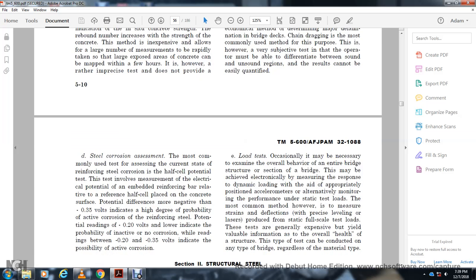Steel corrosion assessment. The most commonly used test for assessment of the current state of reinforcement steel corrosion is the half-cell potential test. The test involves the measurement of electrical potential of the embedded reinforcement bar relative to a reference half-cell placed on the concrete surface. A potential difference more negative than 0.35 volts indicates a higher degree of probability of corrosion activity occurring within the reinforcement steel. A potential reading of -0.2 volts or lower indicates a probability of no corrosion, while a reading between -0.20 volts and -0.35 volts indicates the possibility of active corrosion.